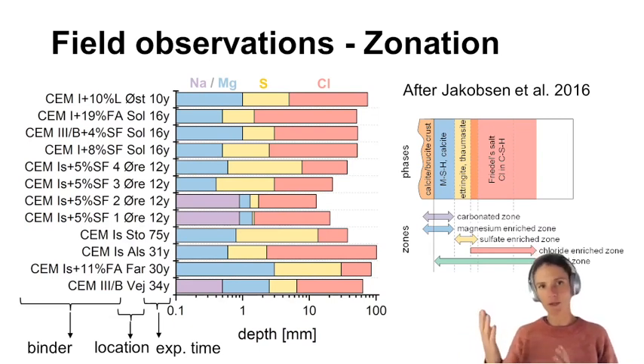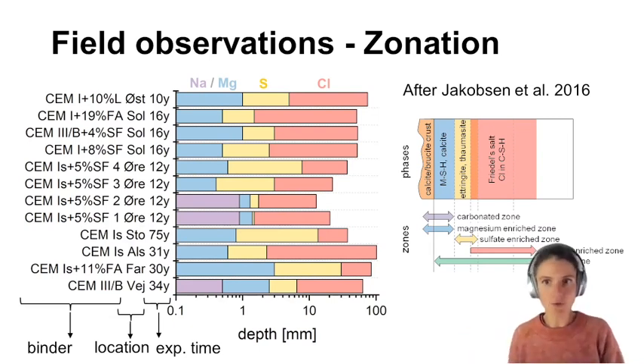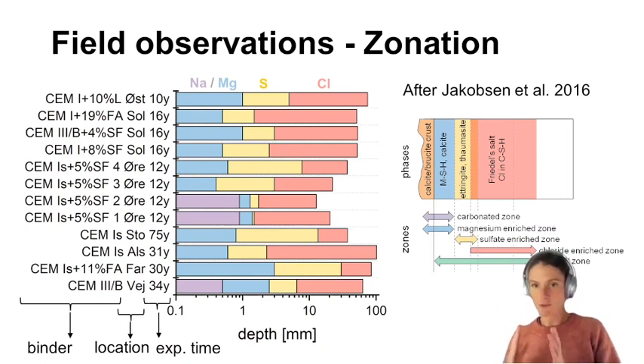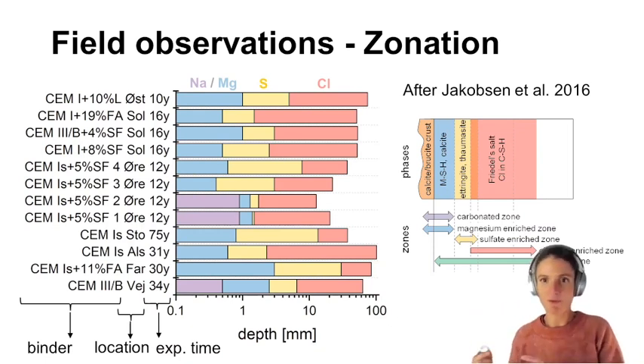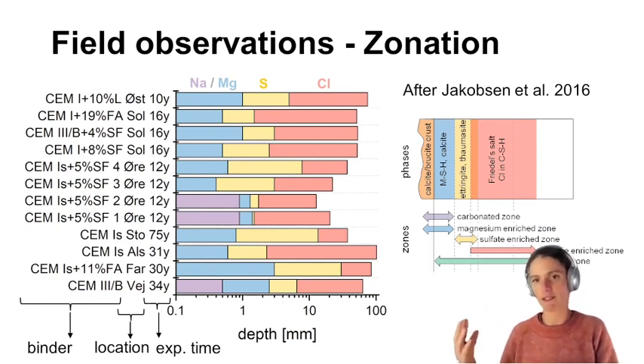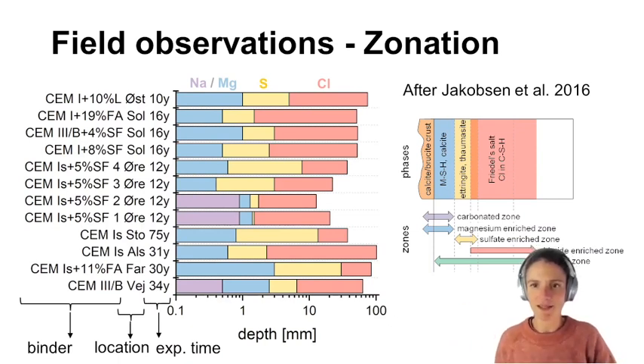And everywhere we could see these blue bars illustrating the magnesium-enriched zone at the surface. In some cases, there was also some sodium in this zone. These zones are then followed by the yellow zone, marking the sulfur-enriched zone. And then deeper, we find a chloride-enriched zone, illustrated here with a red, pinkish color. So it's very clear in this graph, but note that the horizontal axis is in a logarithmic scale. So we're really zooming into what is happening on the surface.